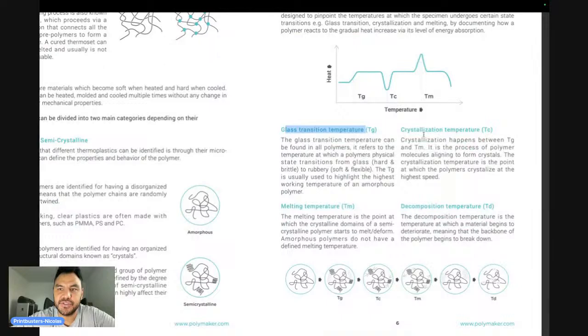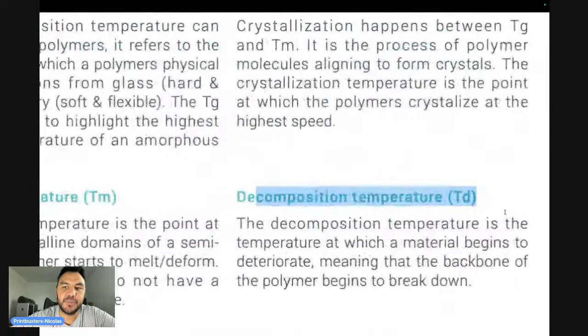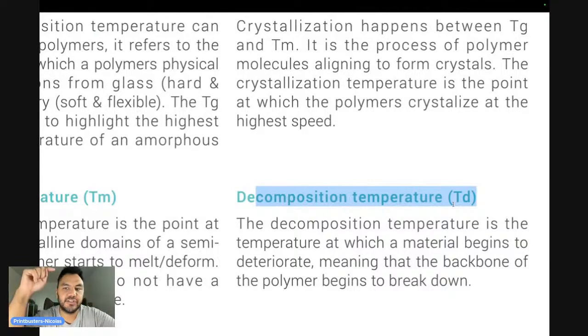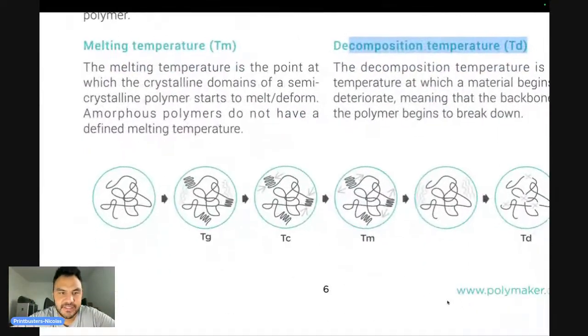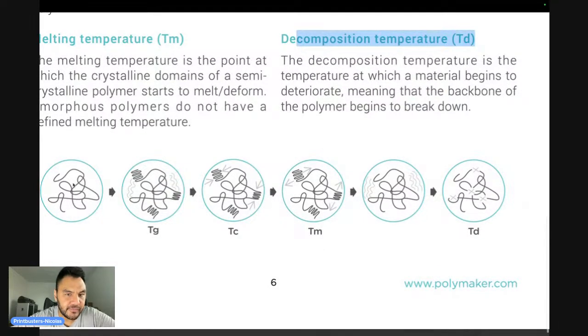Okay, so that's the glass transition temperature, crystallization temperature, melting temperature, and decomposition temperature. Decomposition temperature is the temperature at which you are going to break the primary bond. So at TG you start breaking the secondary bonds, and at TD, the decomposition temperature, you start breaking the primary bonds. You start completely degrading the material. So you can see here, you have the polymer, and at TG the polymers start to move. At TC they start creating the crystal very fast. At TM the crystals are destroyed, and at TD you completely destroy the polymer. Okay, so those are the different temperatures.